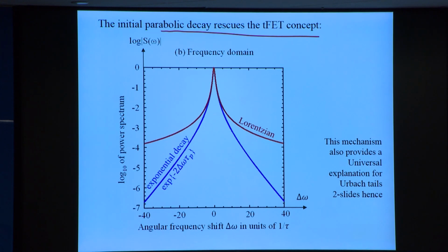People who do material science and spectroscopy often come up with exponential spectral tails, and these are called Urbach tails. These have been very puzzling to theoretical physicists since the 1950s, and many crazy models have been put forward to explain why you get Urbach tails. Maybe you believe in one model, but it would only apply to one material. How come it's universal in all materials? So we'd better have a universal explanation, and what I've just indicated to you is kind of a universal explanation.